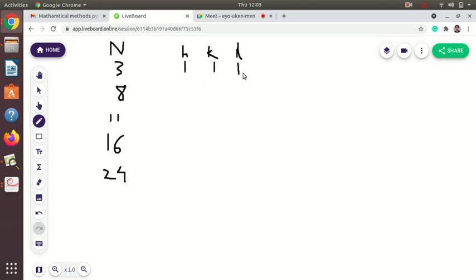The addition is odd, so this is confirmed not BCC. You need not check all values. So this is not BCC. Go to the next. These are all odd, so it might be FCC. Check the next value.